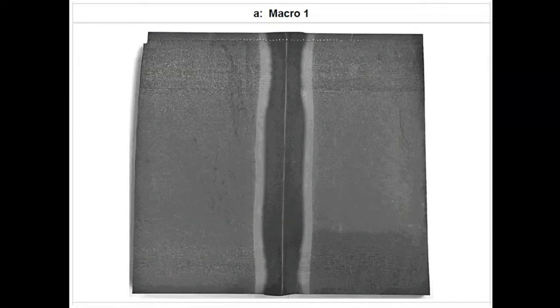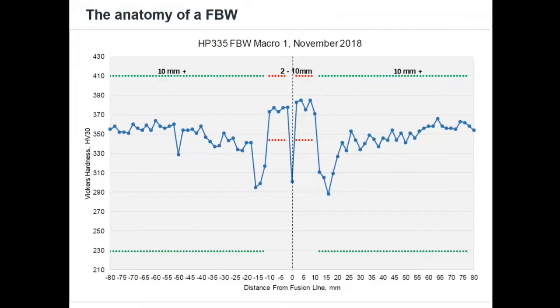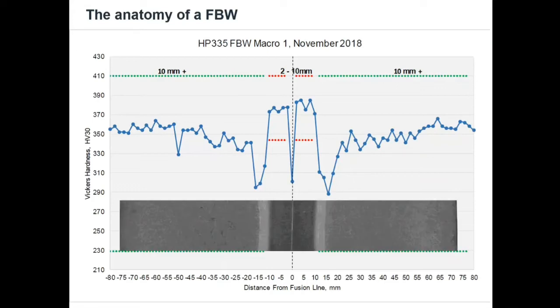The dots you can see along the top of the macro are actually Vickers hardness indents. So we take a hardness indent across the weld, and this is all part of the approval process for the welding plant. So here's what that hardness profile looks like for an HP rail. You can see the parent is typically, I don't know, 355 Vickers there, and you can see the different zones within it. So if we overlay the macro and we look at the critical heat affected zone, what you can see here is you've got a boost in hardness.